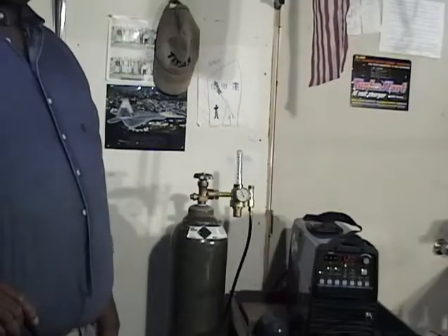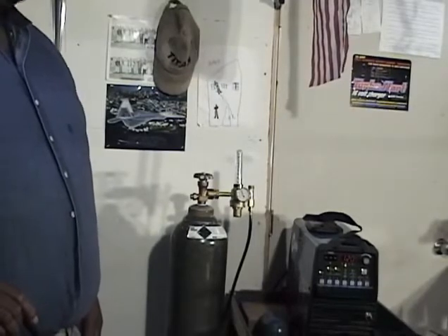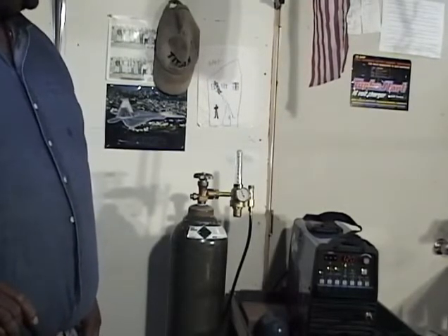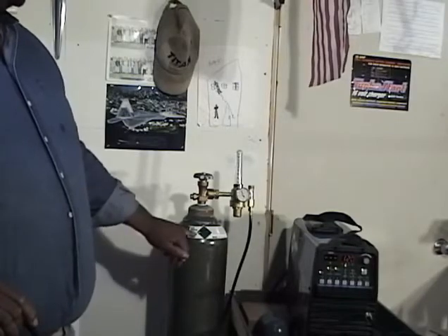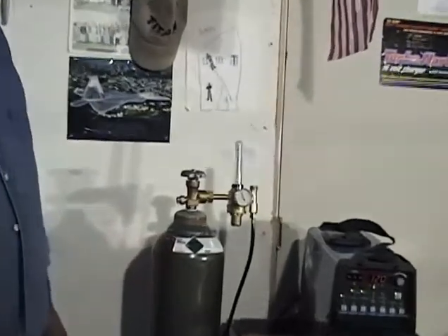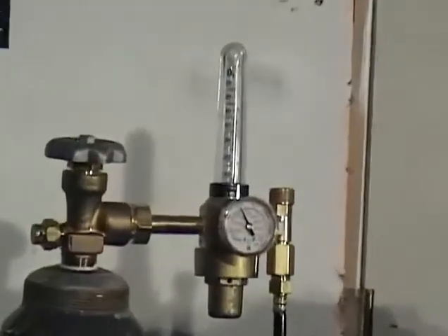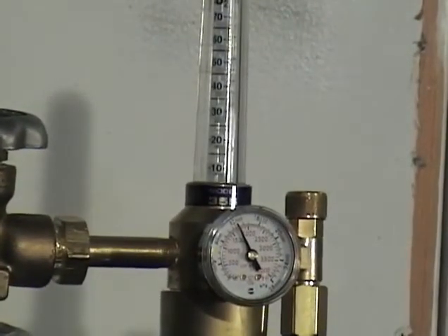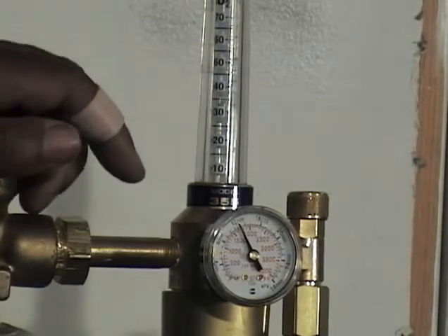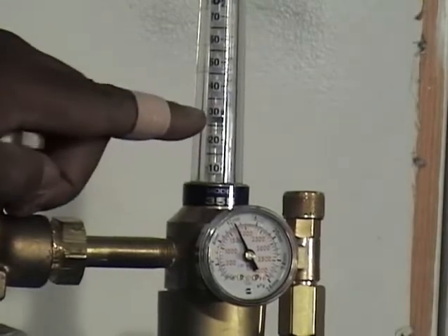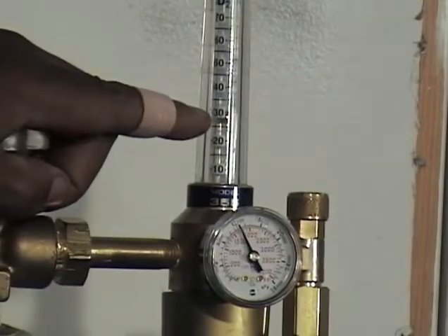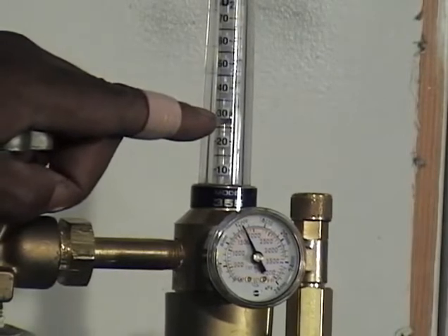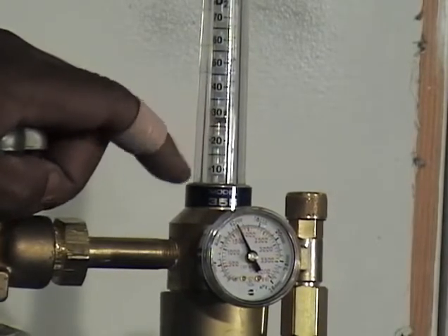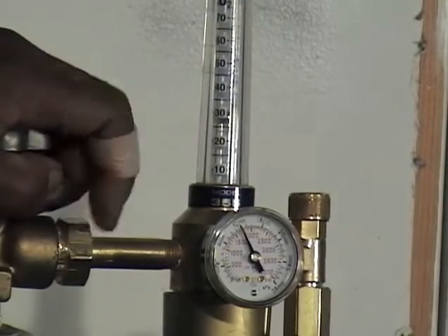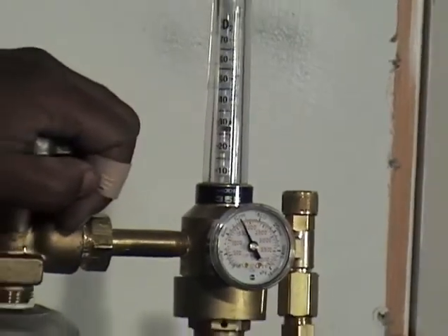Okay guys, we're getting ready to weld stainless steel, and I'm going to give you my reference settings for welding stainless steel. First, we're going to start with our shielding gas. Our shielding gas is argon, straight argon, and the flow rate that I use with stainless steel and titanium is 30 CFM at the top of the ball, and I'll show you that right now. We'll hit the pedal and you'll see that steel ball in there is set at 30 CFM, and that will allow you to have the pretty colors in the stainless, the reds and the blues and the straws, and that's what you want your flow set at, 30 CFM.